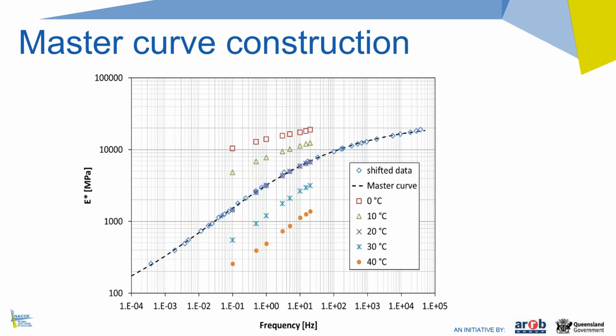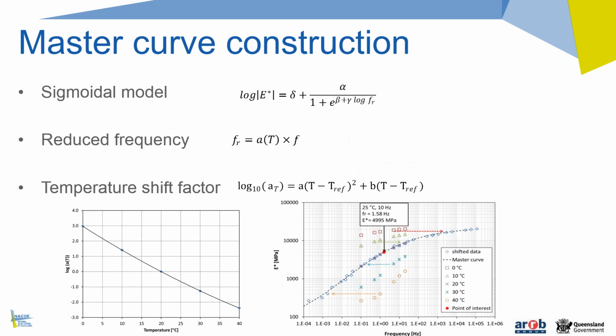That brings me to the master curve construction, and I'll just quickly summarize how that works. As I said earlier, you run tests over a range of frequencies at each temperature, and then we take those results and we shift them in the frequency space to form a single curve as shown in this figure. And we're fitting that data to a sigmoidal model. Now there are other models available from literature. The reason why we went for this model is that it's used in the American Mechanistic Empirical Design Guide as well as the Californian Mechanistic Empirical Design Guide. That's the only reason. Other models are also suitable, but we chose this one. They all give a similar answer. So the sigmoidal model is shown there.